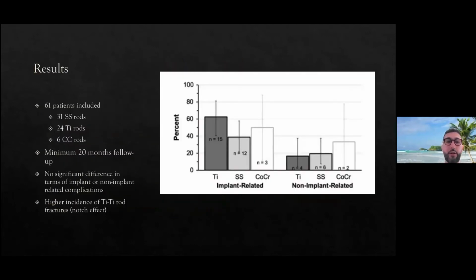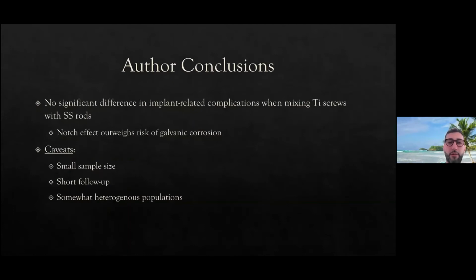And then he retrospectively looked at it. There were 61 patients included. All of them had obviously titanium screws. 31 had stainless steel rods, 24 had titanium rods, and 6 had cobalt chrome. He did 20 months of follow-up. And the bottom line is there was no significant difference in implant or non-implant related complications. There was a higher incidence of titanium rod fractures, which was hypothesized to be due to notch effect, but it actually was non-significant. So he says, the risk of notch effect outweighs risk of galvanic corrosion, but again, not statistically significant.